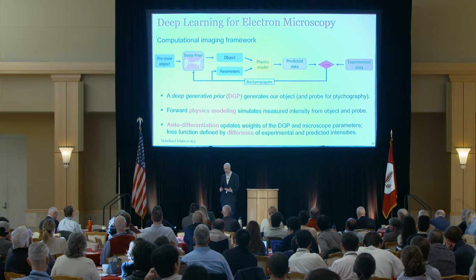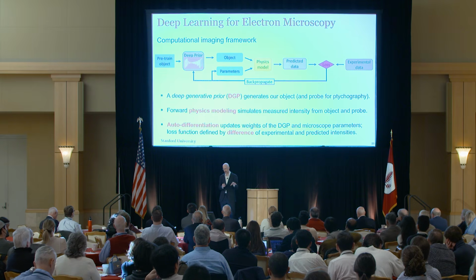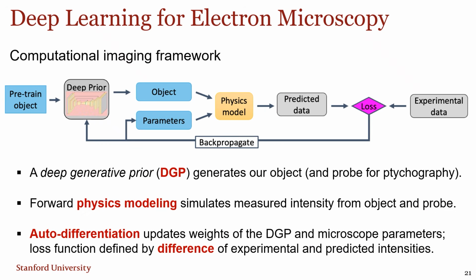So then again, we use backpropagation to update not just the weights of our machine learning network, but also the parameters. For example, in that 3D experiment, what the shifts are between our measurements, the tilts of our samples. And this is a very powerful technique for virtually any inverse problem, because you can see this loop, the only thing that's going to be different in different sciences is that little box called physics model.